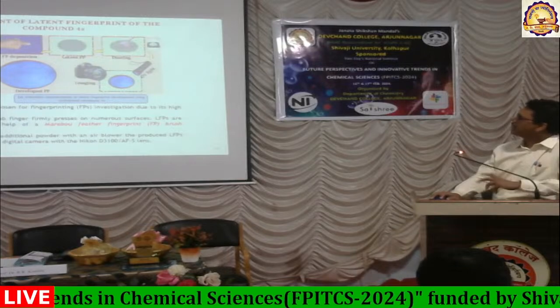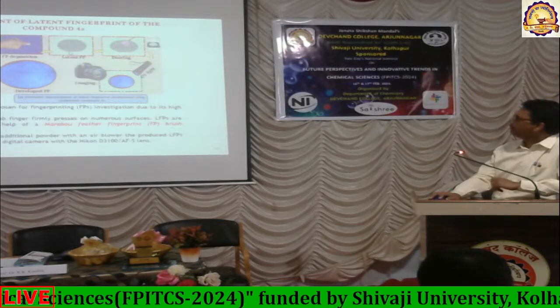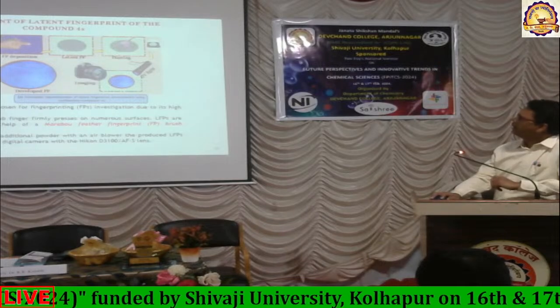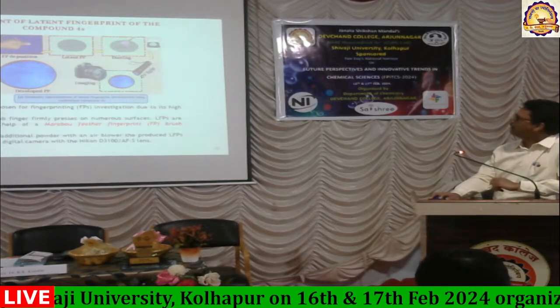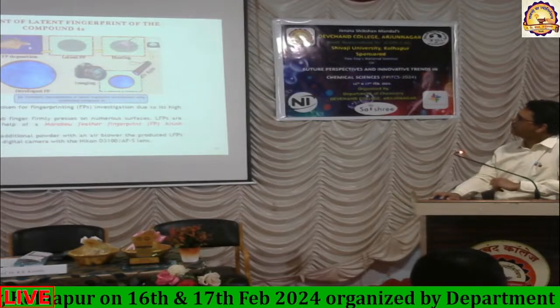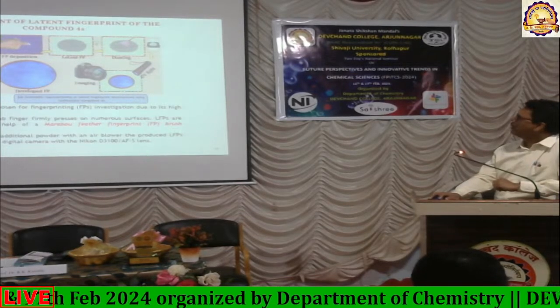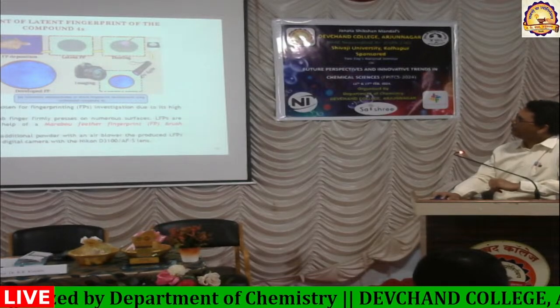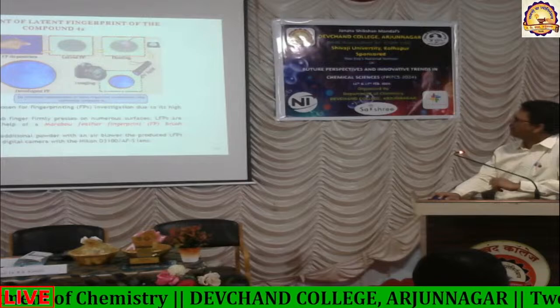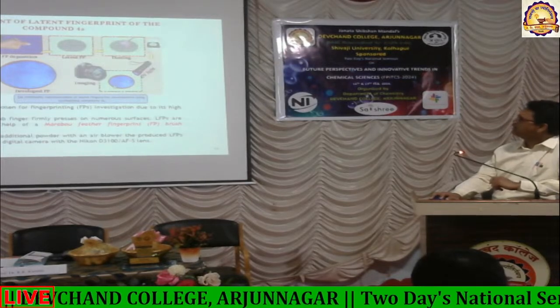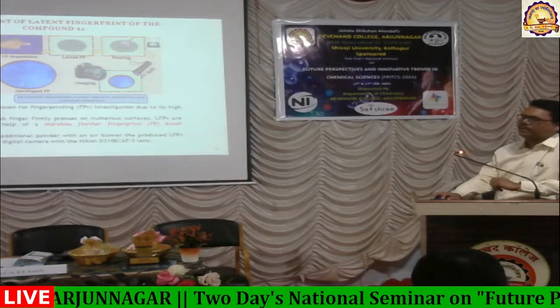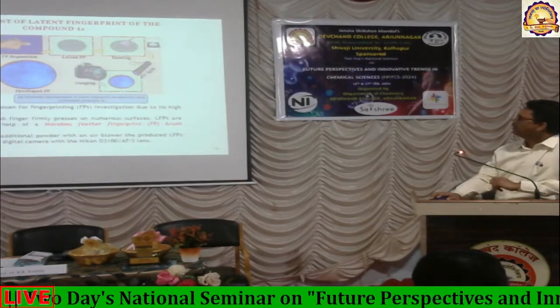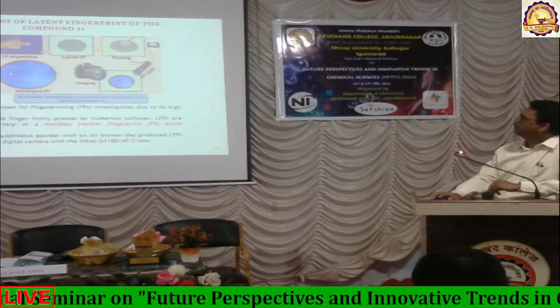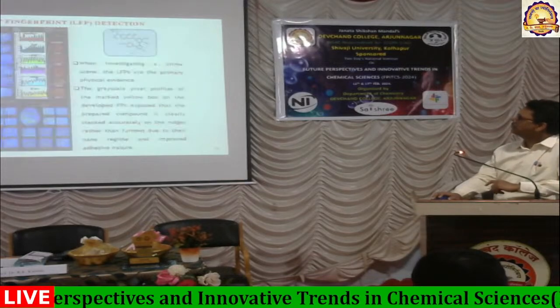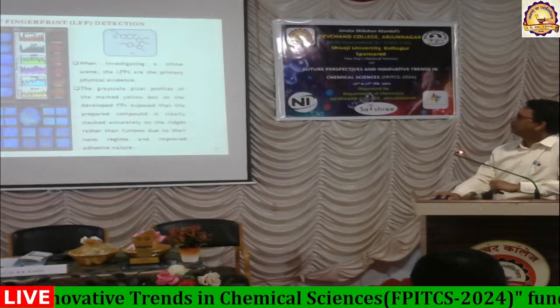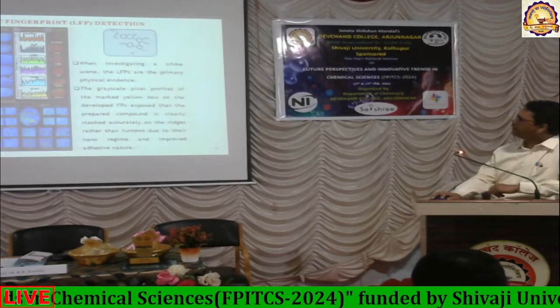So this ink can be a solidified powder, and here is how they develop a latent fingerprint on this. On any surface, a fingerprint is deposited, and on this, the powder embedded with our synthesized compound was dusted, and then under UV light we can see it, so the developed fingerprint can be easily observed. Okay, so this is how we can create a latent fingerprint on any surface. Similarly, yeah. So this is after observation of this fingerprint, what we can see.